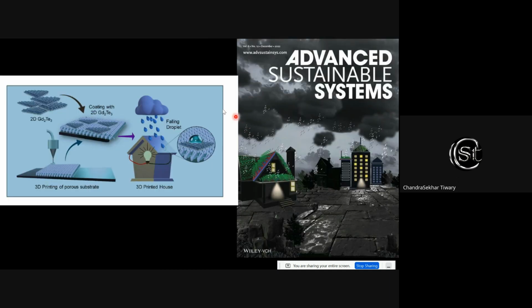Now, one of the interesting 2D materials which we recently made is gadolinium telluride. Gadolinium is a heavy element with a large atomic diameter. Mixing it with tellurium, we make this compound Gd2Te3, and if you exfoliate it, it has a huge surface charge. Now, this surface charge can be utilized for rainwater harvesting.